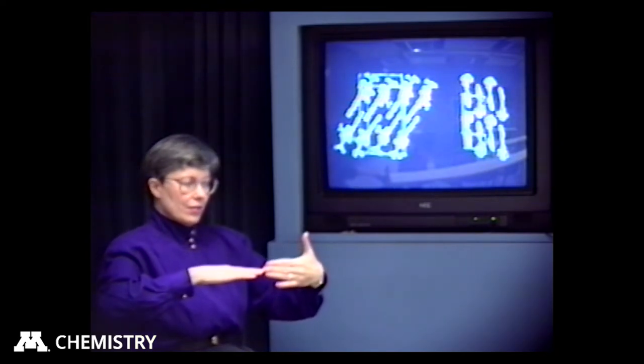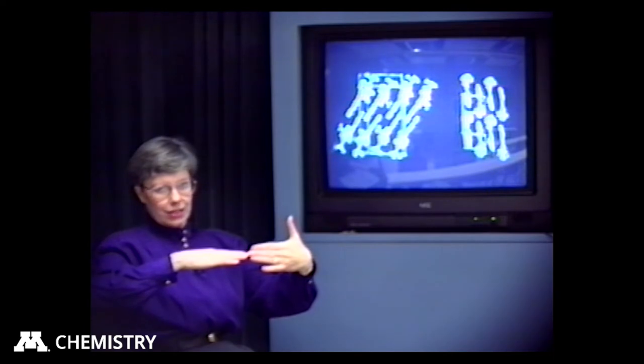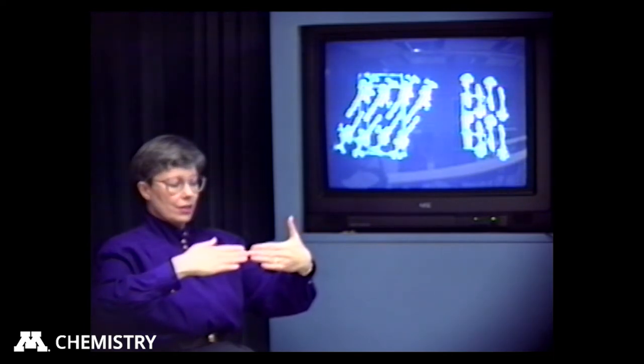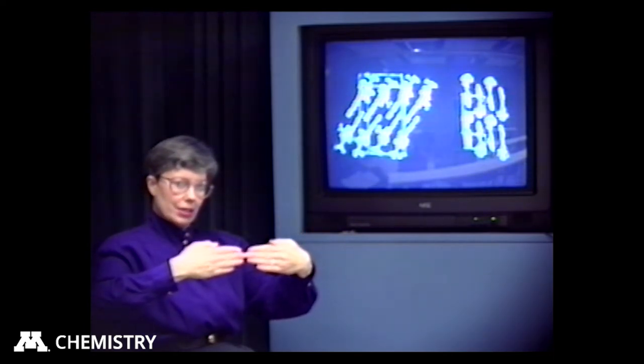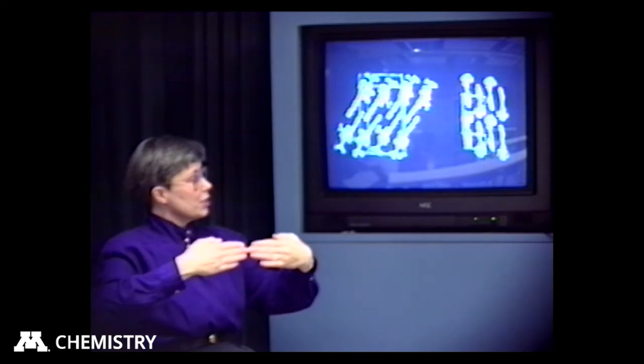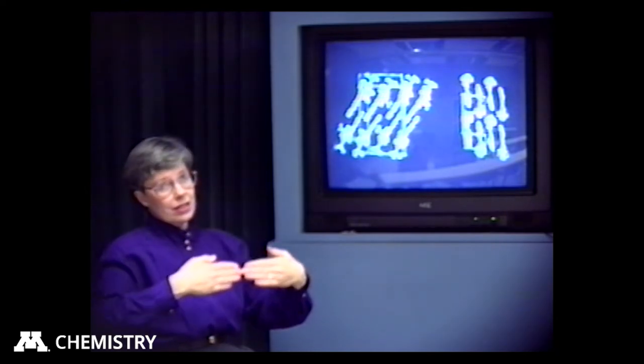Now, why isn't that enough of an explanation? Part of the problem is the starting material, which is yellow, has the phenyl rings twisted slightly relative to one another. We think the red color occurs when that flattens out, because the product red crystals are much flatter than the starting material. So we think that's the origin of the color change. But notice when the expansion takes place, you're still in the yellow form.